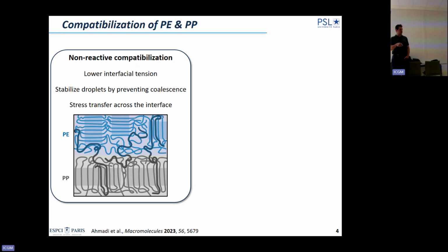And here you have in blue PE, in gray PP, and, tough to see here, in the darker color there are copolymers, which have a good affinity for PE and a good affinity for PP. And in fact they provide entanglement. And ideally, the best solution is that they provide entanglement, and if they can co-crystallize, then you really improve the mechanical property. So the ideal system probably would be to have co-crystallinity in both phases, because this is how you will probably improve the properties the best.